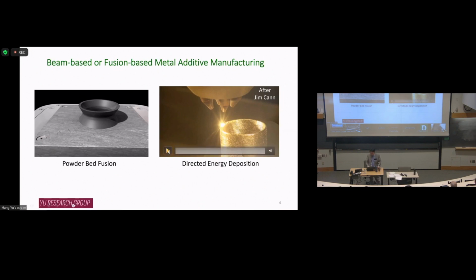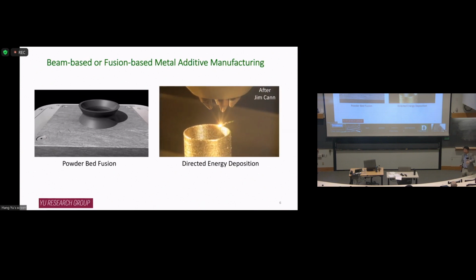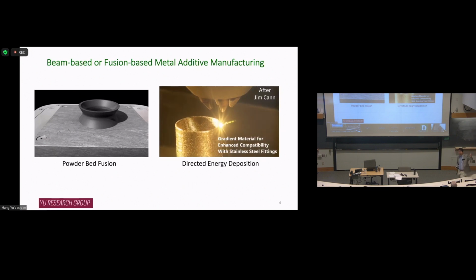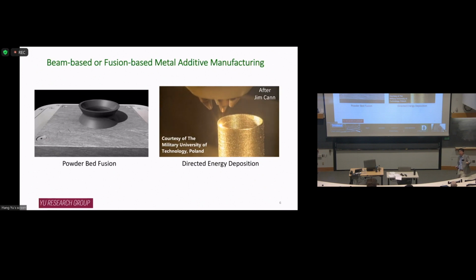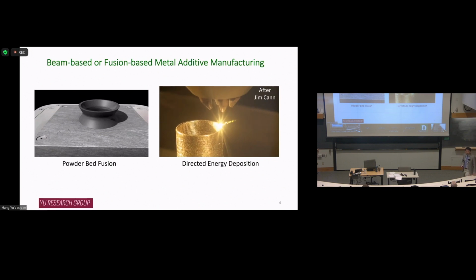There's another process here called directed energy deposition. In this case, you have multiple nozzles. Each nozzle supplies a stream of powder. At the same time, in the center, there's an infrared laser applying energy to the location you want. So the material and energy come to the same place at the same time, so you can deposit material to the locations you want. The cool thing about this is you can manipulate your powder supply rate, so you can do in-situ alloying, you can do functionally graded material here. So you see the 2 processes have very different configurations, but the underlying physical principle is the same. It's based on melting and rapid solidification. So this is a fusion-based additive manufacturing process.